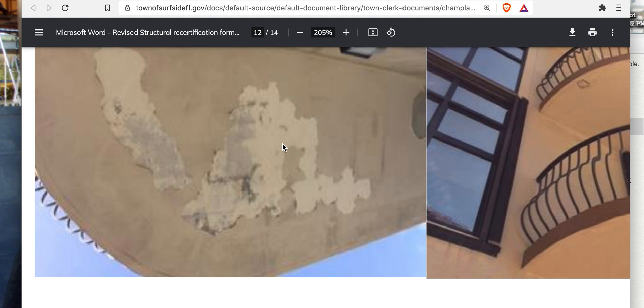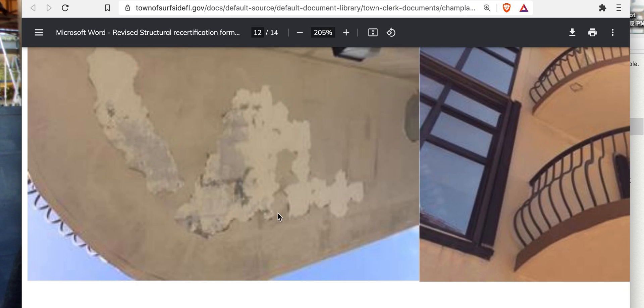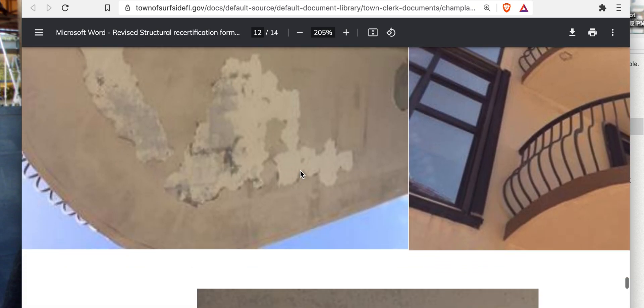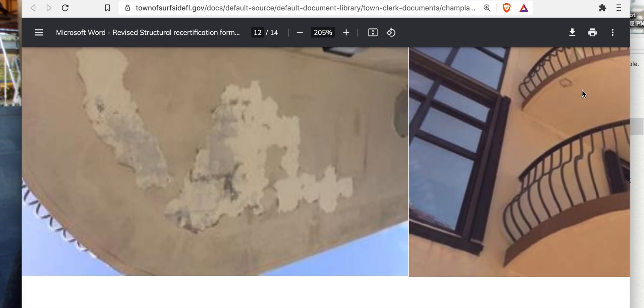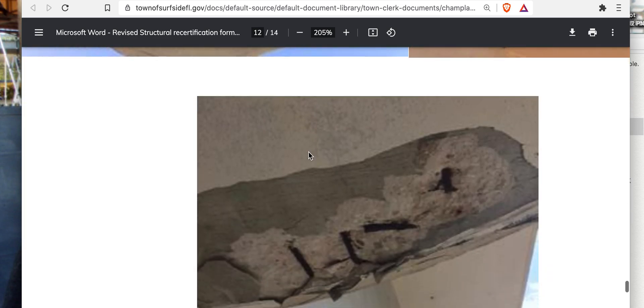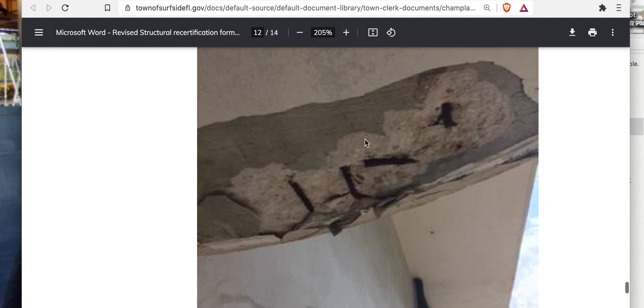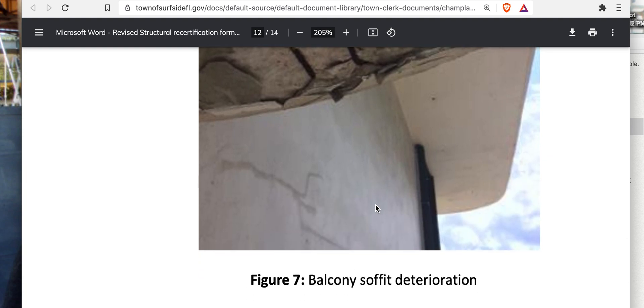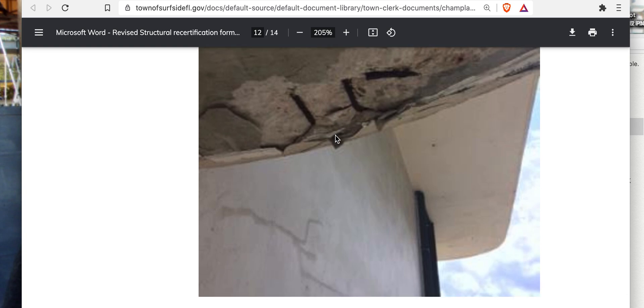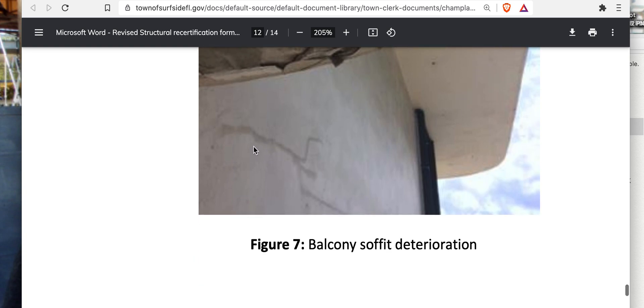The repair process would include compression testing the existing concrete, checking the steel, and then determining how far back to go on the repair per deck or across all decks. They're all life safety, so the cost shouldn't stop you. Each one of these decks deserves a core sample because each one has families that are going to use and occupy them.